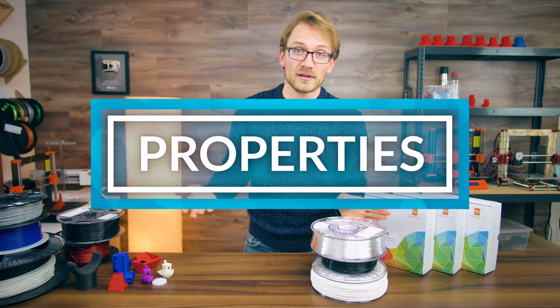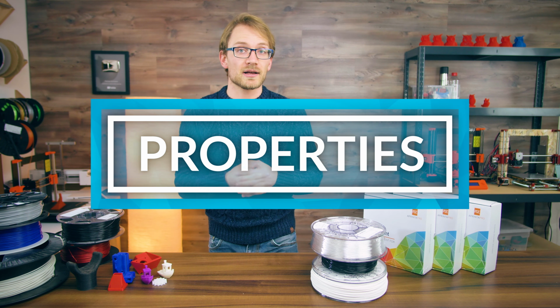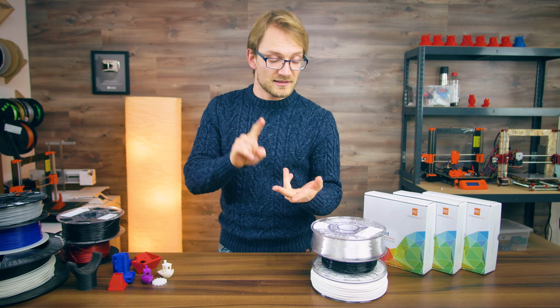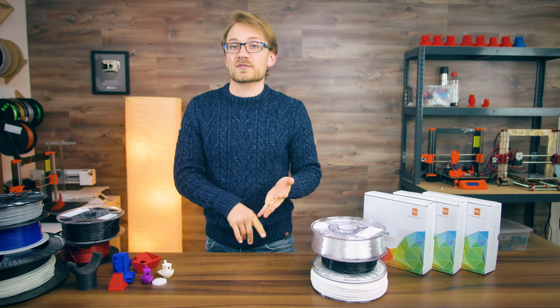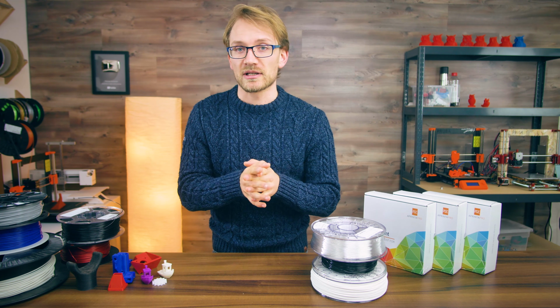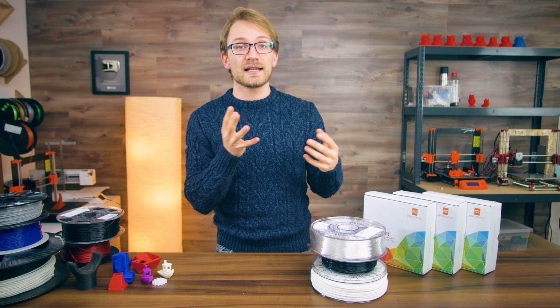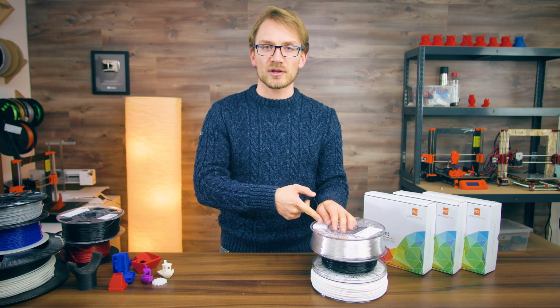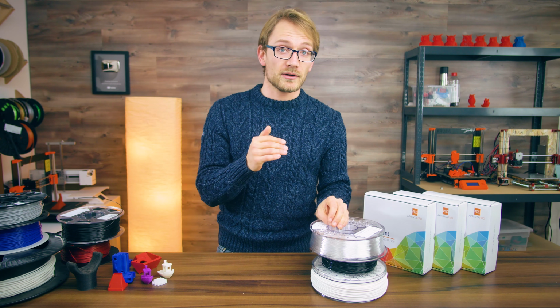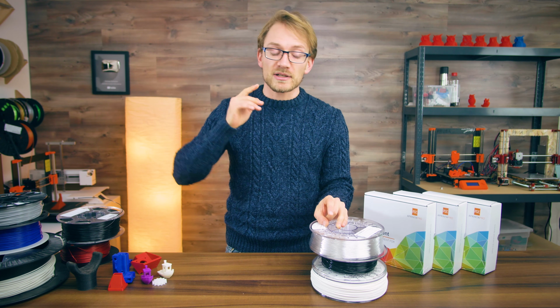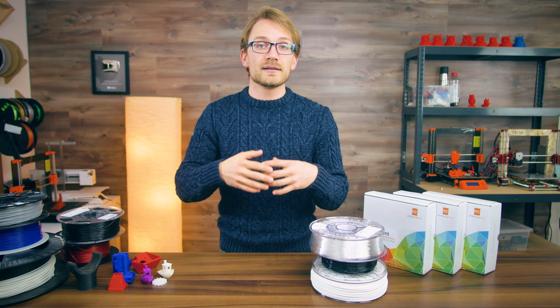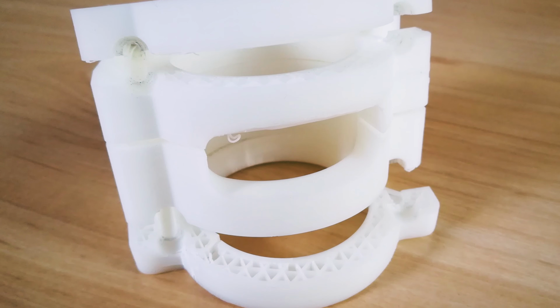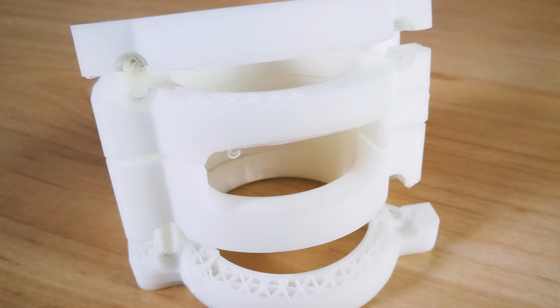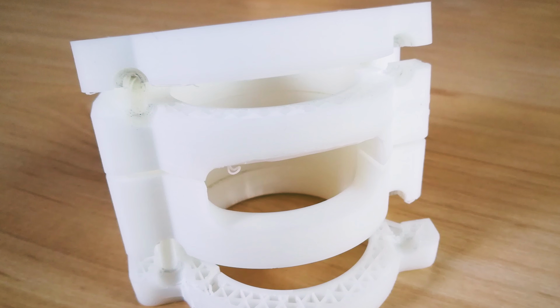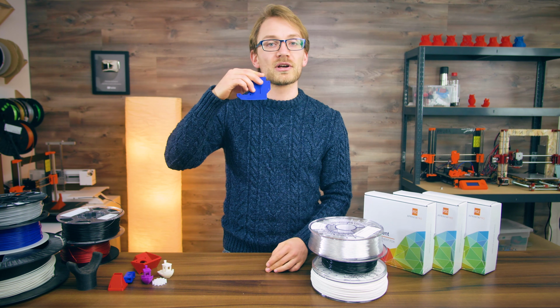So yeah, properties, what are those? What you'll typically hear is something like, oh yeah, ABS is strong, it's temperature resistant, but it warps and it smells. Okay, let me get this straight. Parts printed in ABS and ABS-likes, except for maybe polycarbonate, are typically weaker than most other plastics, especially if printed wrong, like in a cold environment. That's also where you'll see ABS warp and crack along the layer lines because it doesn't bond well enough to the cooled down previous one.